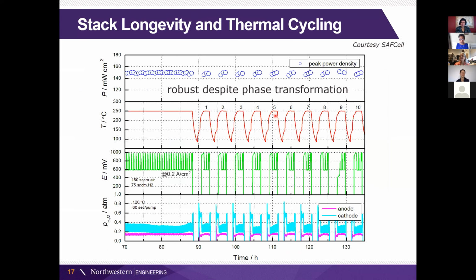The other thing is that I mentioned that there's this phase transition. So despite this phase transition, we can cycle the temperature through the transition and recover the power density. So this is the peak power density, which is that top point in the power curve that I showed you, is quite stable over several hundred hours. This is only up to 150, but it continues. And the voltage is also quite stable. So everything looks great. At thousands of hours, we start to see some degradation in the cathode.